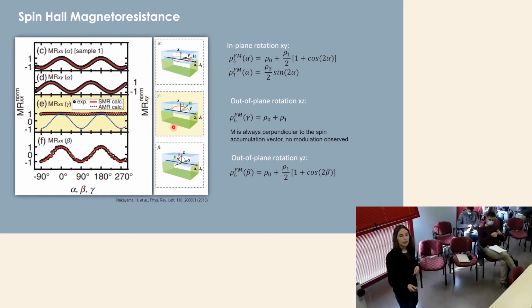For example, in here you're seeing the magnetic field rotated in the plane between the current and the out of plane direction. And this is expected to give no modulation because here the magnetization is always pointing perpendicular to the direction of the spin accumulation. So from the injection point of view, there's no difference here. But if we scan the magnetic field in the plane that contains the transverse directions, we are again expecting to see a modulation with two times the angle.